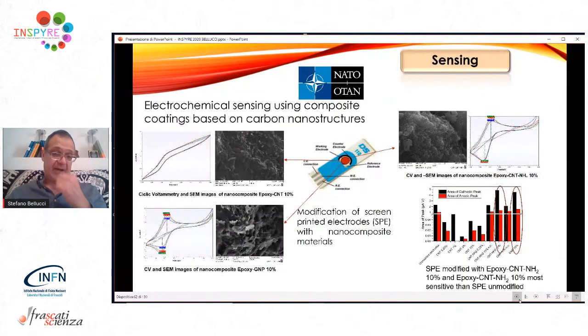Here's what we achieved by electrochemical sensors in our project. We used composite materials where we inserted carbon nanotubes modified by aminic engineering molecules, and graphene nanoparticles. And the performance, as indicated by the peaks in the graph, is not good for carbon nanotubes and is instead excellent for carbon nanotubes modified as well as for graphene, because you see clearly peak-shaped curves. That testifies the performance of the sensor.